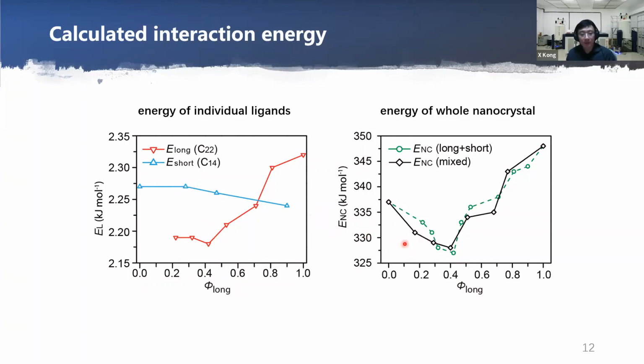However, the selective deuteration is quite costly. So we try to do a simpler measurement on samples with both protonated ligands. Of course, for both protonated ligands, we want to be able to separate their individual contributions. Nevertheless, the simple analysis correlates very well with the results of the partial deuteration. So the black line is based on the both protonated experiments, and the green line is the summation of the selective deuteration. So this indicates that the dynamic volume analysis is pretty robust with respect to the experimental uncertainties.